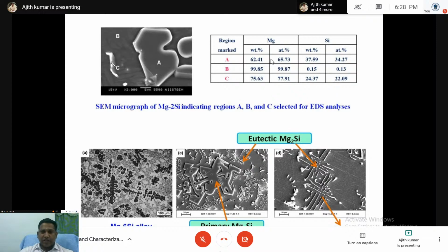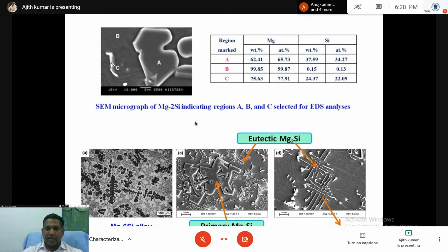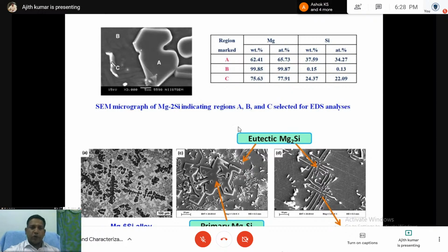From the point, it is 65.73 atomic percentage magnesium and 34.27 atomic percentage silicon. That means 2:1 magnesium and silicon there. So we are calling it Mg2Si. So this phase is Mg2Si. It is confirmed using SEM microscope and EDAX analysis. Then again you can see after that, in the white region of the microstructure, some different phases are there.